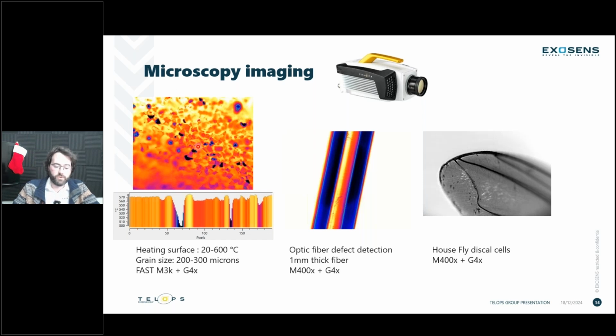You were able to bring that surface from 20 to 600 degrees Celsius while maintaining that imaging. And by doing just simple processing here, you can see that non-uniformity of those grains' emissivity. So all of these are at the same temperature, of course, but the surface microscopic differences and the material differences from some of those grains showed a pretty drastic change in temperature just due to change of emissivity properties.